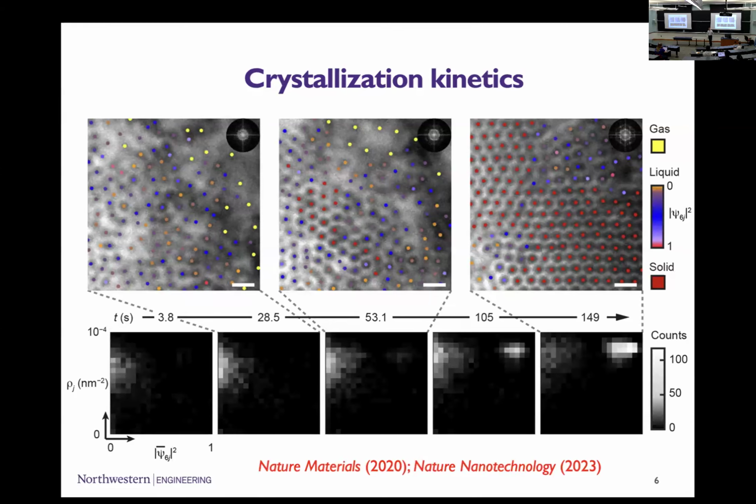The issue is this: if you actually look a little deeper into what is the interaction between a pair of, let's say, any type of atoms, and how does that compare to their size? That range is maybe 50% of the size of the atoms, maybe even more. If you go to colloids, let's say a micron-sized colloid, the interaction range is maybe 10 nanometers. That's 1% of their size. So they behave very differently. They don't feel each other until they're very close, and then they stick.